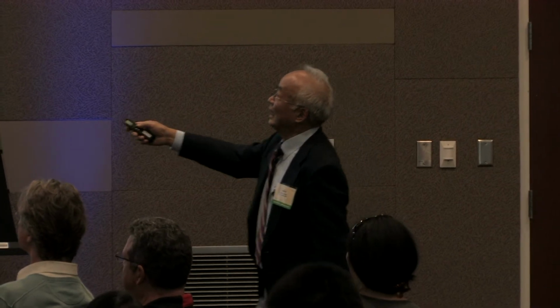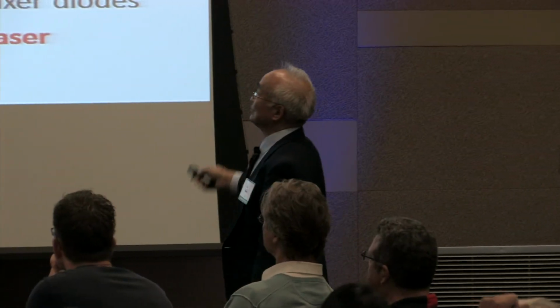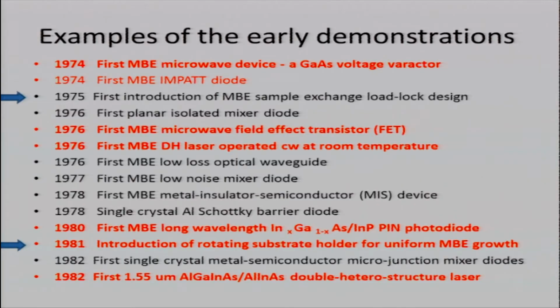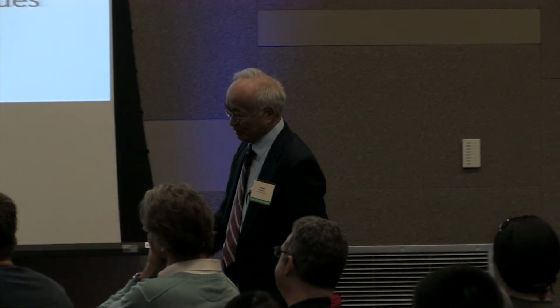So then I mentioned we introduced load-lock exchange in 75, and then very importantly, by 1976, I demonstrated the first MBE double heterostructure laser lasing CW at room temperature. If you can do that, you almost practically can do any other devices because it's most critical to make that CW room temperature lasers. And then continue to develop MBE.